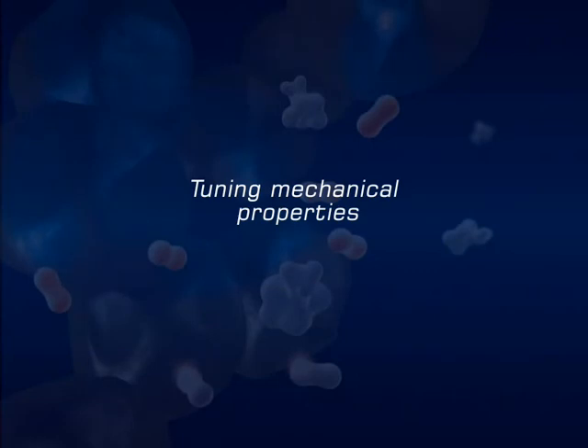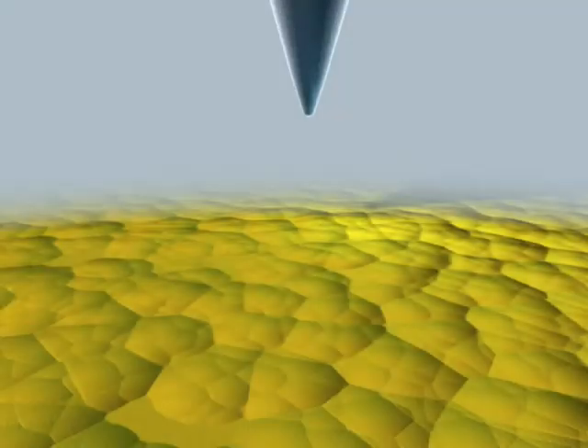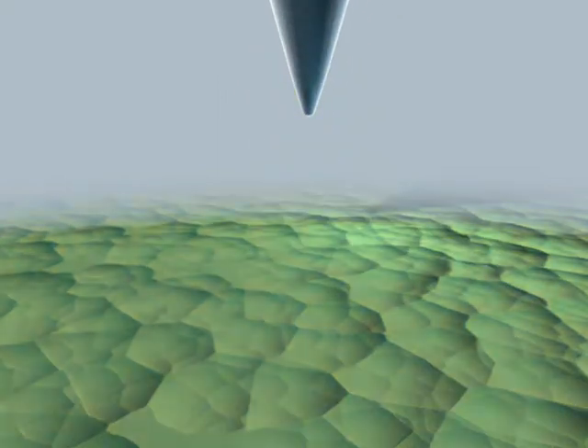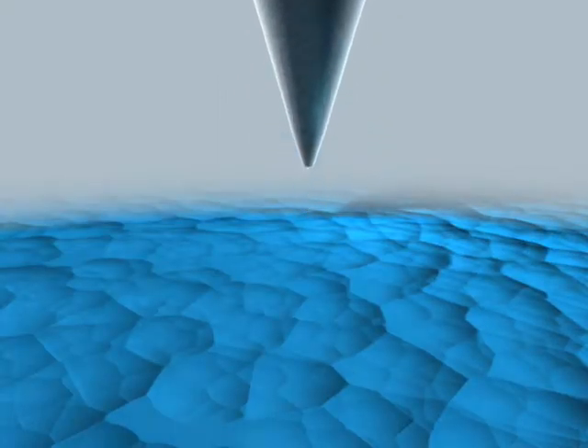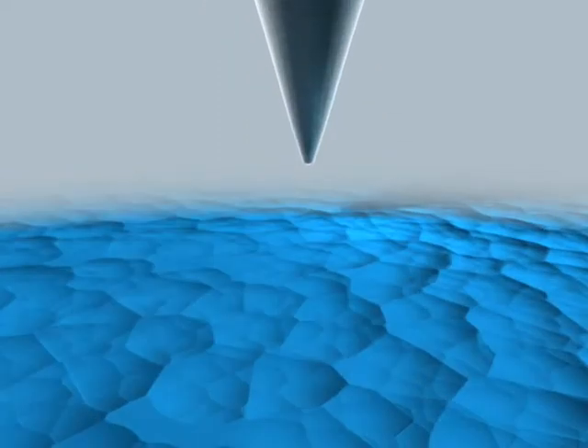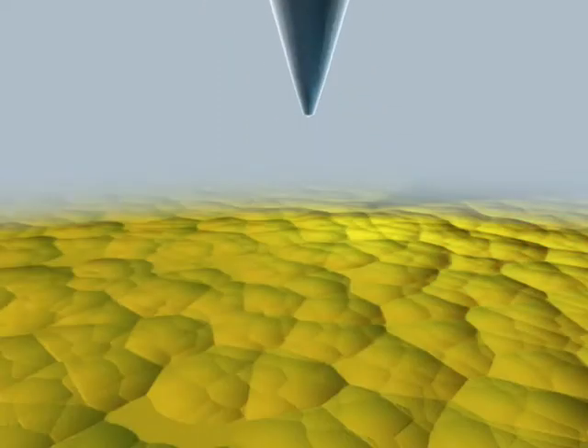To add a further dimension, electrical stimulation can be used to tune mechanical properties in situ. Using an atomic force microscope probe, we can measure such properties in the nano-domain, and we can show that the modulus and other mechanical properties are significantly altered by electrical stimulation.